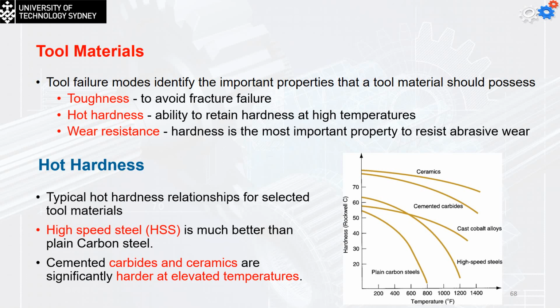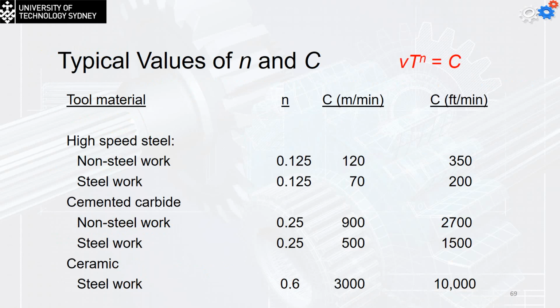The typical values of n and C in the Taylor equation change according to the material we are going to use. You can see that for high-speed steel, for non-steel work, for example if I'm going to cut aluminum, the value of n is going to be 0.125, but the C value is going to be 120. That means the life of the cutting tool is going to be longer if I use it on non-steel work. For steel work, the value of C will drop, and this means that the tool life will drop as well.